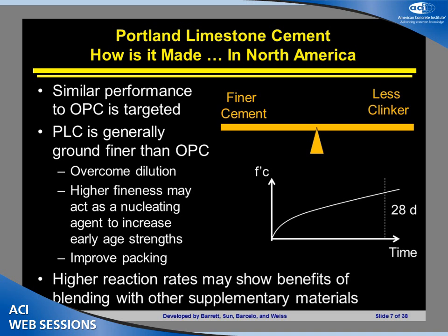So if you look at a normal strength development curve for our OPC, if we deal with our PLC, we're grinding it a little bit finer. We're going to see more rapid strength development initially, and then we're going to see that rate of strength gain slow down a little bit. But this is mainly influenced by the fineness of the material. The higher fineness helps us because it can act as a nucleating agent, as Paul mentioned. It also helps us because it can improve particle packing.